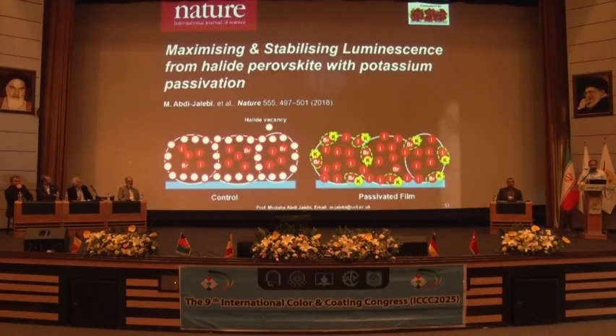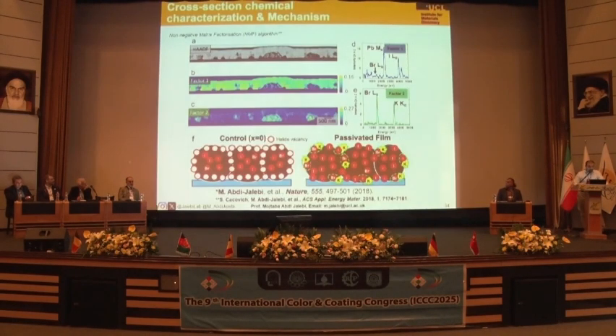This perovskite material is an ionic material, so it has defects within the crystal structure. To make it very simple, I'll make a schematic over here for you. This shows very simply the grain structure of the perovskite, and these white circles show the defects within the crystal structure. What we have done in this work is implement an additive, potassium halide or potassium iodide, where you can fill all of these vacancies with the additional halide that you are putting into your system, and also lock them up at the interface. In this case, you can gain stability.